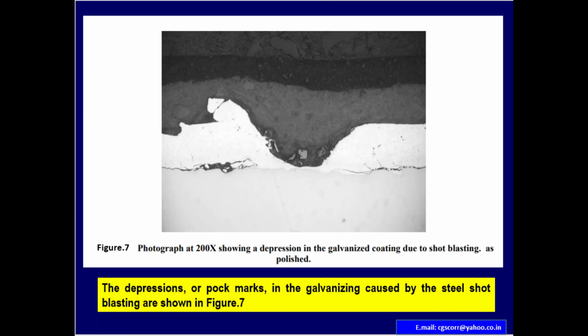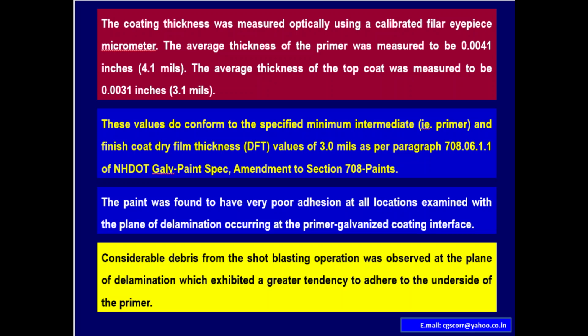Figure 7. Photograph at about 200 magnification, showing a depression in the galvanized coating due to shot blasting, as polished. The depressions are pock marks in the galvanizing caused by steel shot blasting, as shown in figure 7. The coating thickness was measured optically using a calibrated filar eyepiece micrometer. The average thickness of the primer was measured to be 0.0041 inches, that is 4.1 mils. The average thickness of the top coat was measured to be 0.0031 inches, that is 3.1 mils.